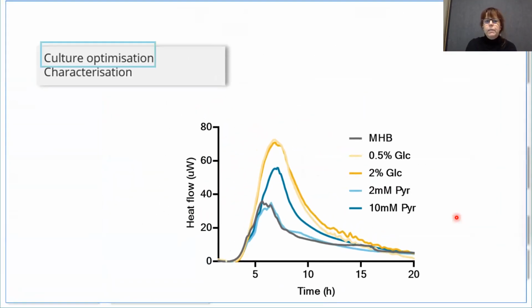Then another example here is to look at culture optimization. So if you want to have an optimal culture of whatever you are growing, a probiotic, for example, you may have, like in the standard media, this is the gray curve here, you have that activity, and then you put additives. This is different carbon sources, both the carbon source and the amount of carbon you put into it. We can see it doesn't affect the initial growth, but we can see it affects the metabolic activity, maybe after growth, that if they have more nutrition or more carbon in this case, they can grow with a higher activity, or they metabolize with a higher activity.